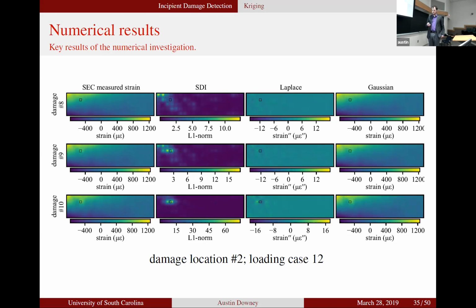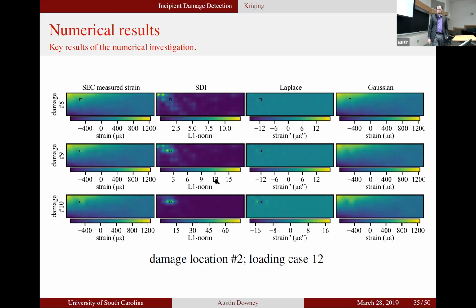These are just moving the damage location. So here we're going to move the damage location to the right. Again, same situation. We have a damage situation where it's relatively small and we can't pick it up. We start to pick it up and then we can pick it up clearly. And then we're always outperforming the Laplace transformation, and the Gaussian we're outperforming quite well.